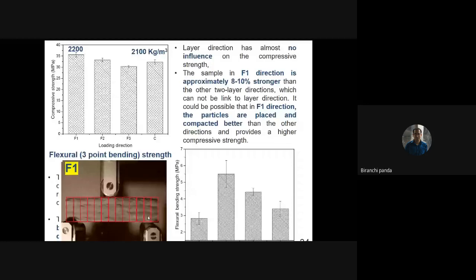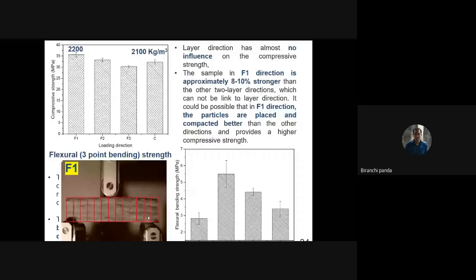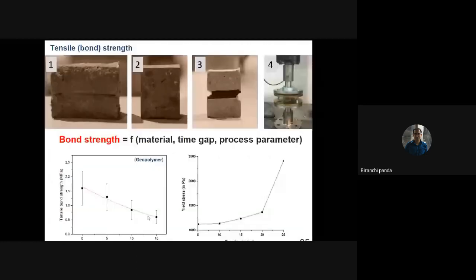Because as you know, in 3D printing, we are depositing the layers one by one. So the layer strength, the internal bond strength between these two layers is very critical, and it is going to severely affect the F1 direction. So for that reason, we started to investigate the tensile bond strength between two layers. We printed the material and investigated this property by changing the material, time gap, and process parameter.